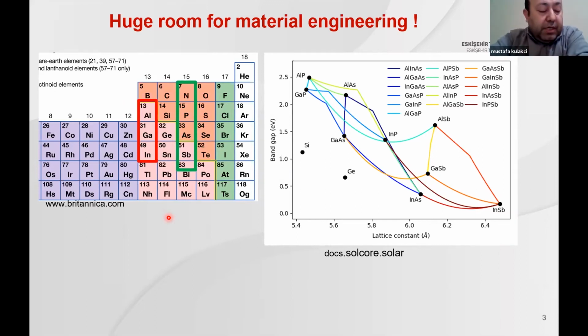And the important thing is that you can do a huge amount of engineering. Inside of a band gap, you can easily tune by changing composition, and there is also a huge room for lattice constant. Lattice constant is very important for crystal growth technology, so you can play with lattice and band gap very easily. I have not put gallium nitride-based structures here, but there is gallium nitride somewhere here, and indium nitride somewhere here. They are also very important in optical and optoelectronic technology.